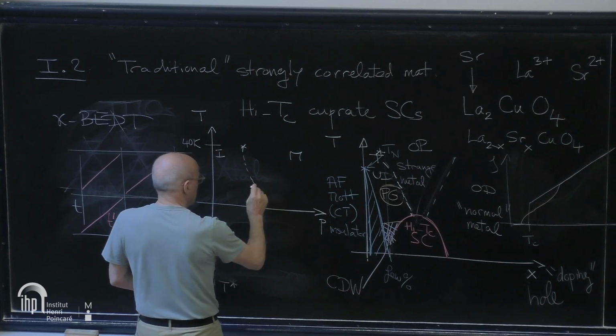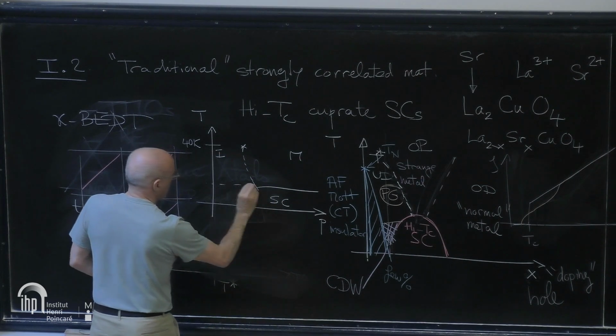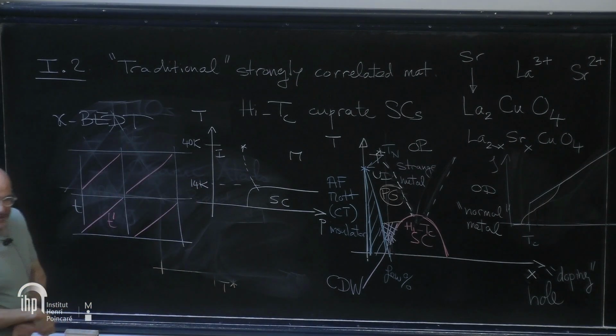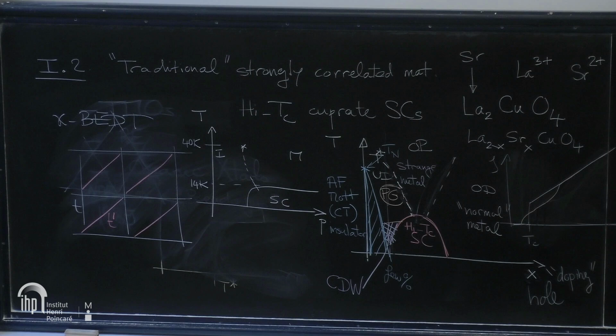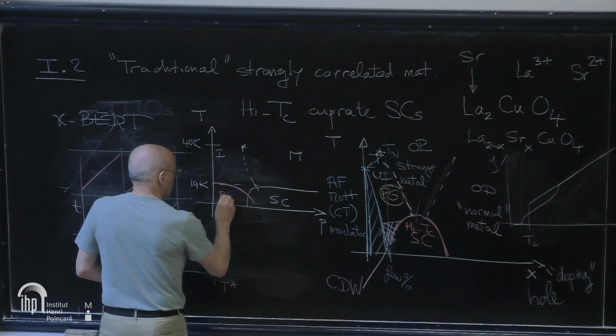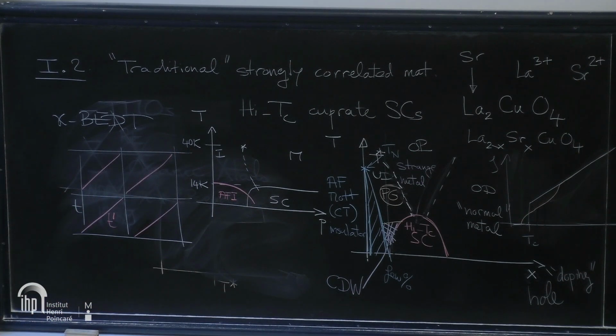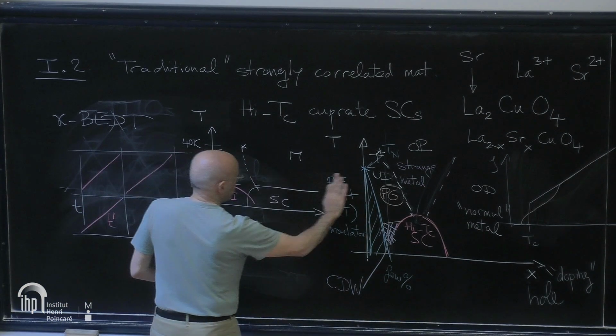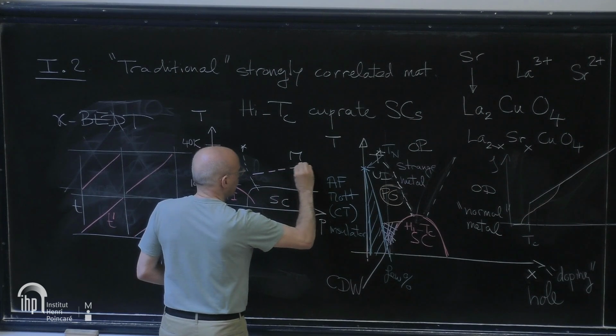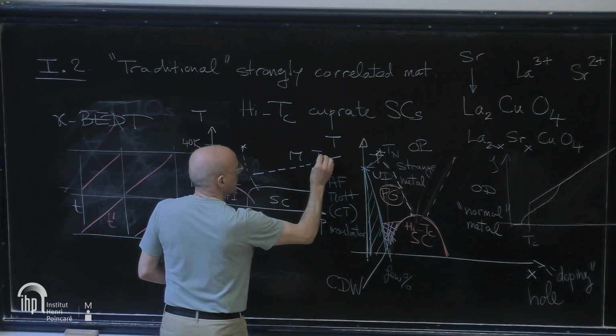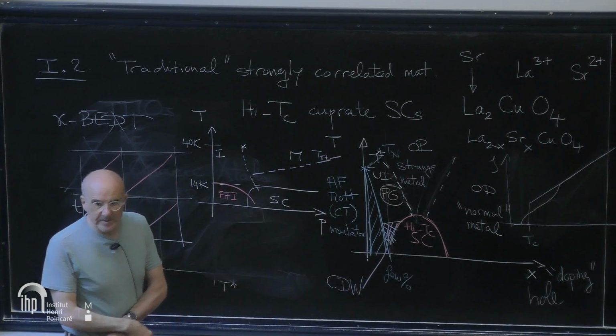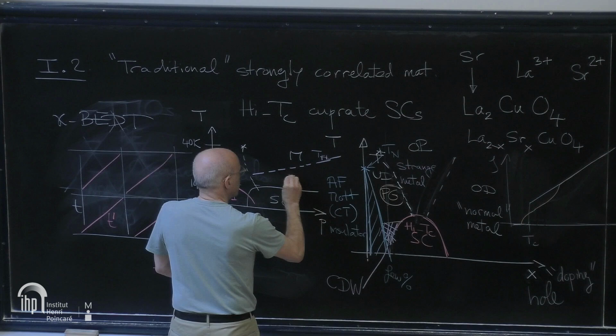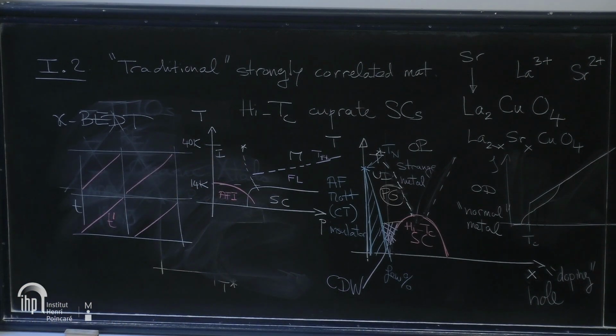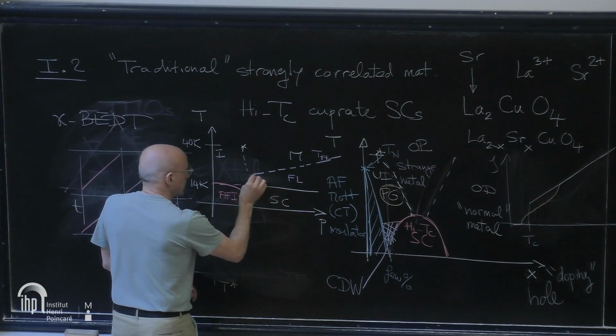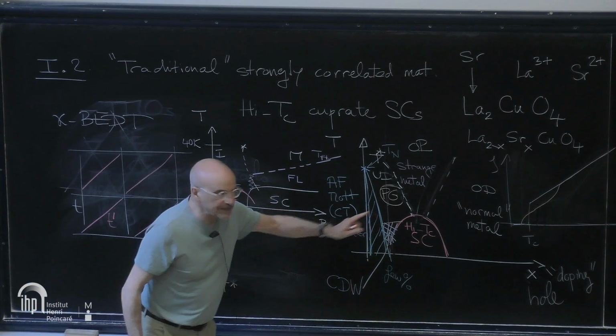And when you cool down the metal, it becomes a superconductor with a transition temperature which is actually quite high as compared to the bandwidth, 14 Kelvin. So this is also a high Tc, in relative terms, superconductor. And here there is, again, an antiferromagnetic insulator. But in contrast to the cuprates, at least over a very large range of pressure, these systems are Fermi liquids. So there is a Fermi liquid coherence scale below which coherent quasi-particles do form, and the resistivity is T squared. There may be a very tiny region near the metal-insulator transition with some hints of a pseudogap, but this is a very narrow range.